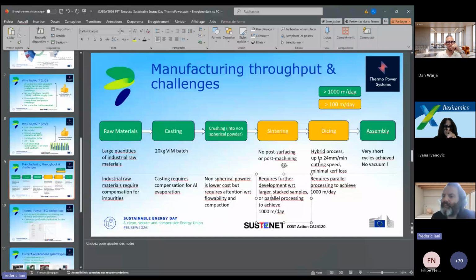Then the dicing is a big challenge, because conventional dicing approaches like electron discharge machining or conventional saw cuts can be very slow because our material is very brittle. It can be as slow as 2 millimeters per minute, but we could achieve an equivalent cutting speed of 24 millimeters per minute, and we really minimize the kerf loss.